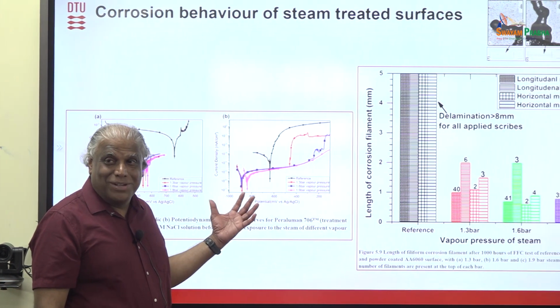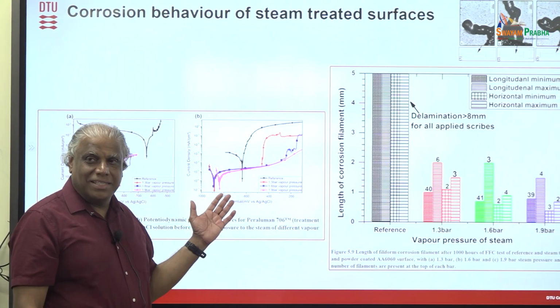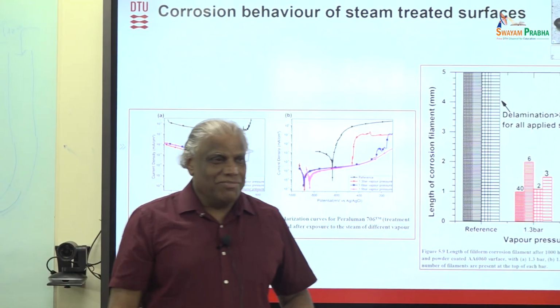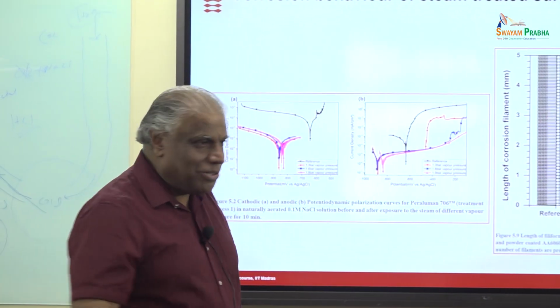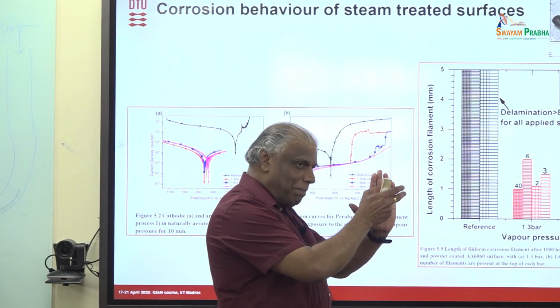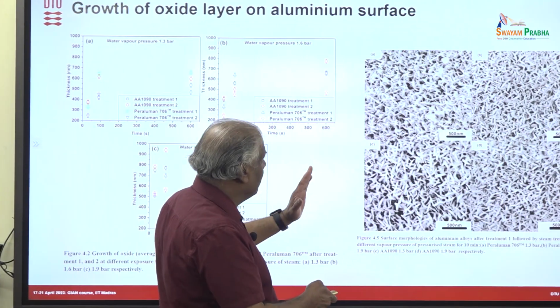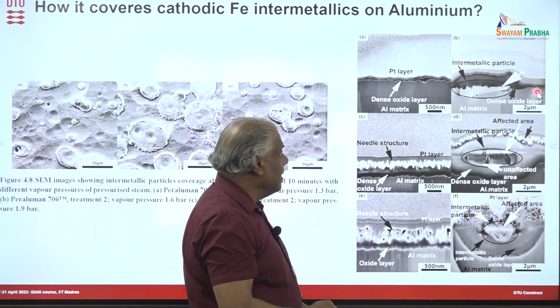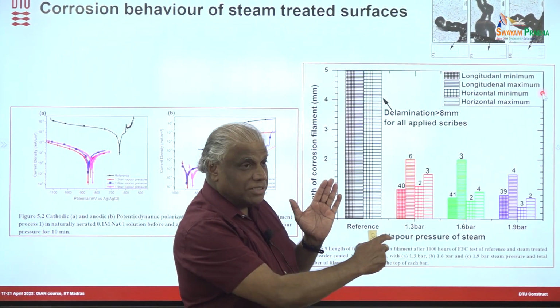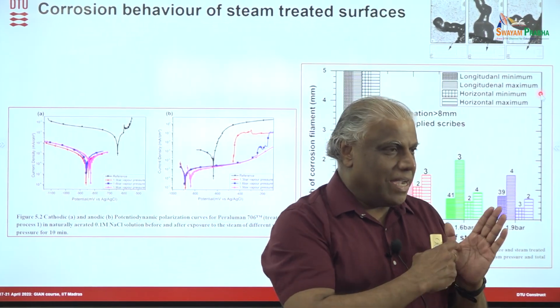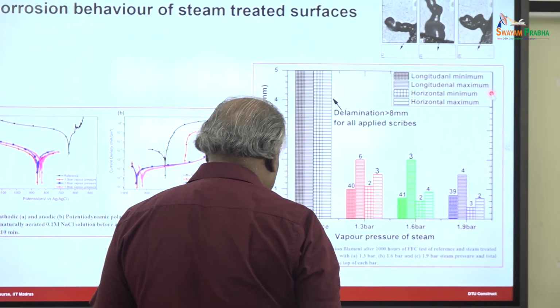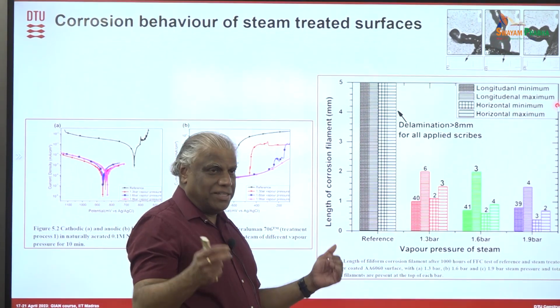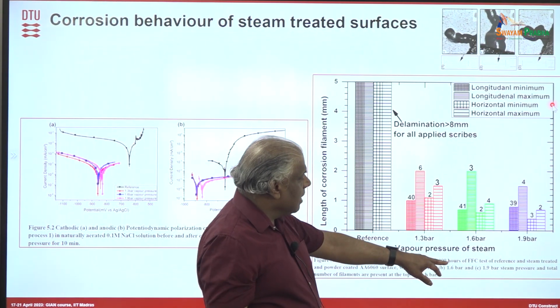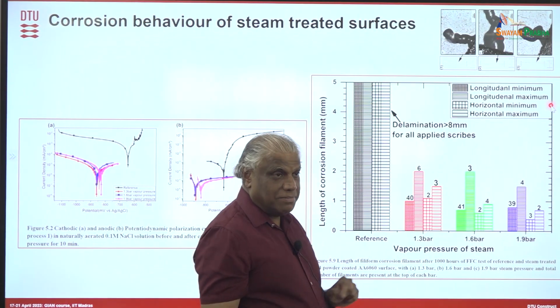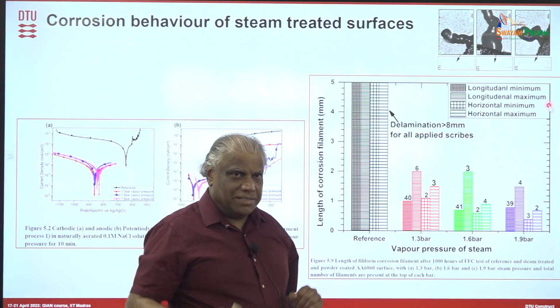Commercial people will not accept that result, because this is taking the coated surface, putting it in the solution, and analyzing it from a corrosion point of view. That's not enough. They want to see whether it will work with a paint or not. So the automotive industry comes, you can give all these results, they just throw them away. What they want to know is that you take that coated surface and put a paint on top. After putting the paint, you make a scratch on the paint, mimicking a crack formation on the paint. Then you put it into salt spray testing, and see over 1000 hours how much the corrosion is penetrating from the scratched area. This is what they want to know.